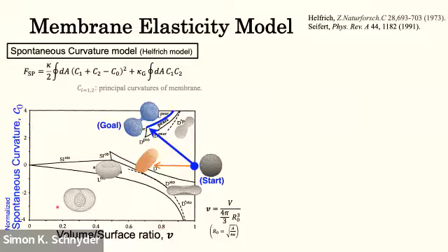And the second important parameter is the spontaneous curvature of the vesicle membrane. So zero spontaneous curvature means zero natural curvature. That means the growth of the membrane, or generation of excess membrane area, leads to a tube-like shape. And then according to this phase diagram, to obtain the reproduction cycle spontaneously, the vesicle membrane should take this blue pathway. And to take this blue pathway, the membrane requires a positive value of spontaneous curvature.